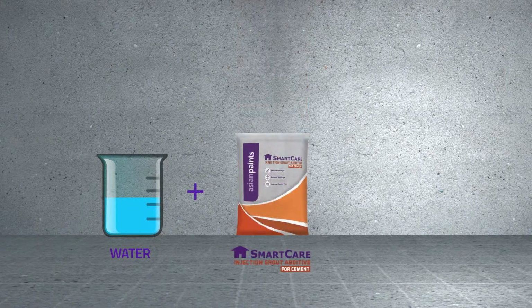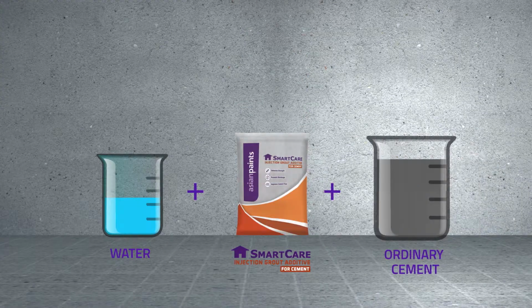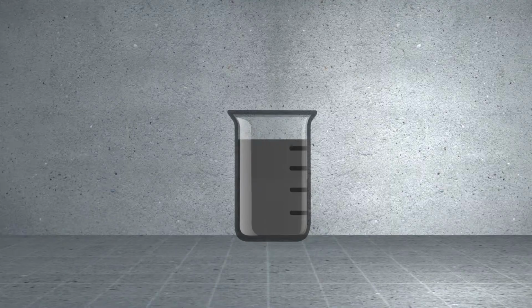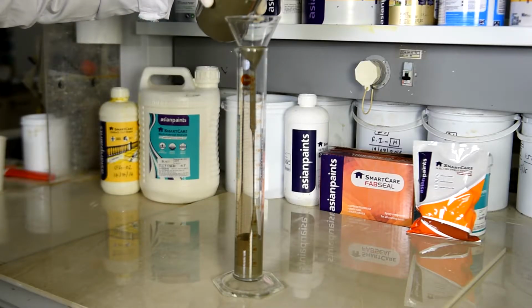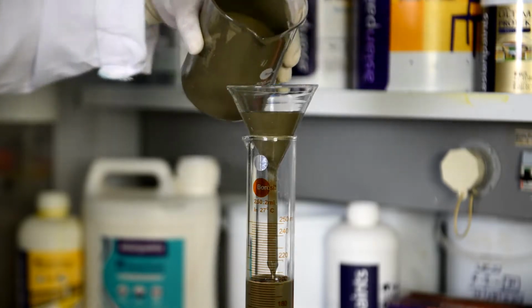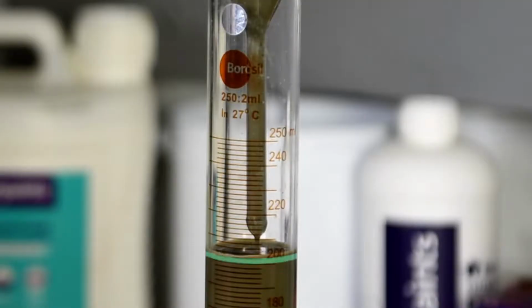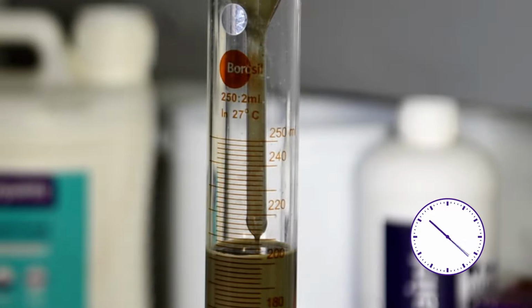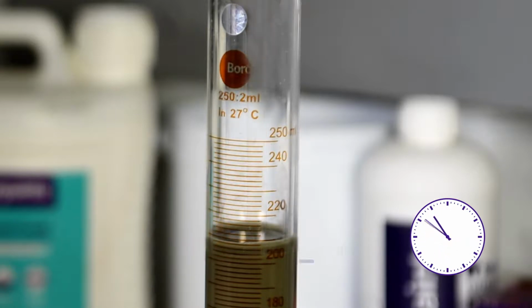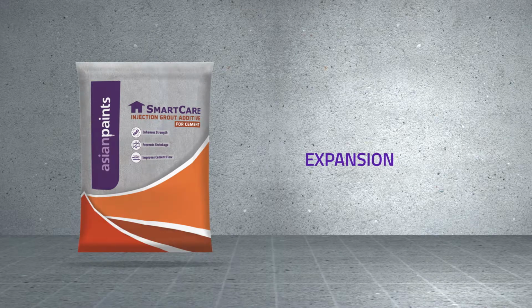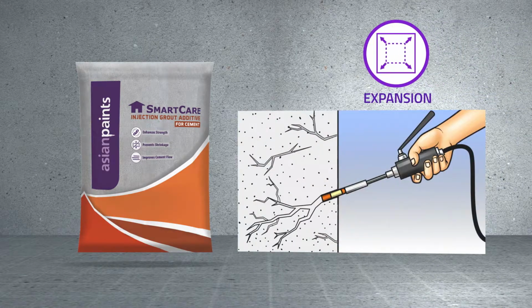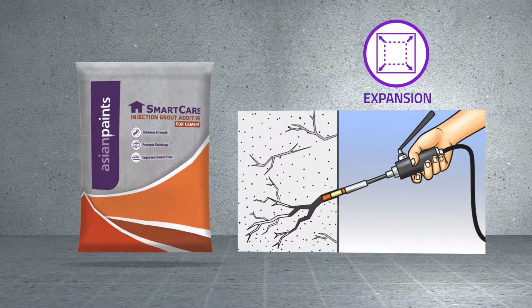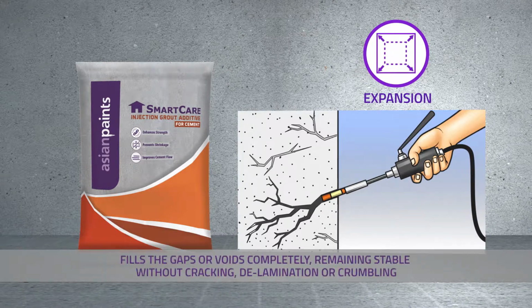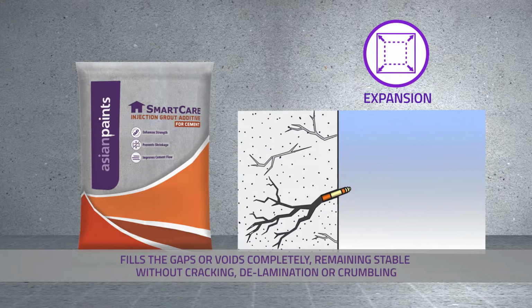Water, SmartCare Injection Grout Additive and cement are mixed as per the recommended ratio and filled in a measuring cylinder up to the 200 ml mark. After 1 hour, we observe that the volume has expanded by around 4 ml. Thus, due to this expansion property, the cement which has been mixed with SmartCare Injection Grout Additive can now fill gaps or voids completely and remain stable without cracking, delamination or crumbling.